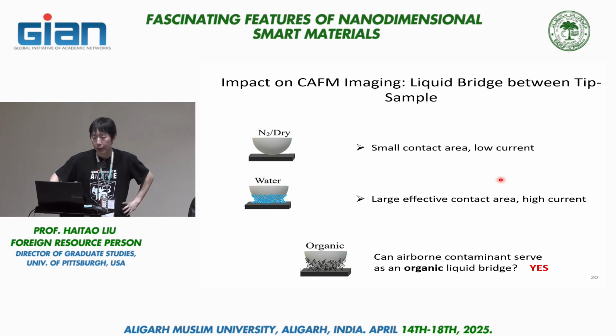Now, in this context, conductive AFM becomes very relevant. It's a highly popular analytical technique to analyze surface electrical conductance. And in the context of conductive AFM, it is very well known that the liquid bridge can significantly impact the conductivity measurement in CAFM imaging. So the basic idea there is any surface you expose to air, people know and understand that there's a layer of water. Okay. So pretty much all surfaces you work with in air, you should assume there's a layer of water. What people never thought about before was there should be a layer of hydrocarbon as well.